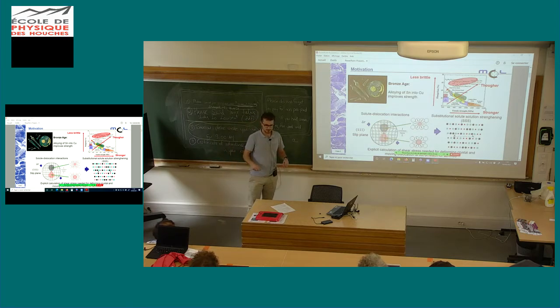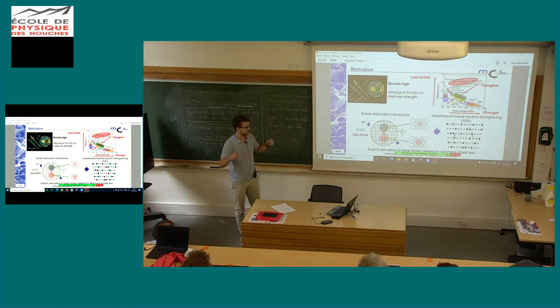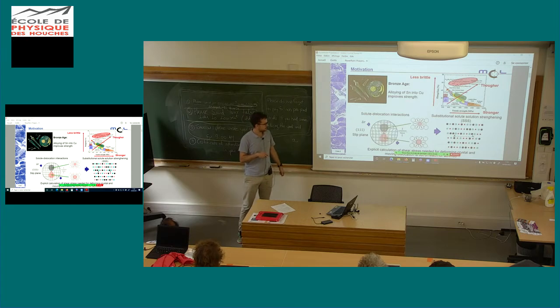So what is basically happening? If you put solutes into your alloy, it will locally distort the lattice, it will contract in some places, it will expand. And these distortions of the lattice interact with our extended defects, our dislocations, which are responsible for the plastic deformation. So you create local energy configurations for the dislocation that are favorable or unfavorable, which in fact will lead to some macroscopic strengthening effect by making it harder for the dislocation to move through the crystal. Of course, it's impossible to do an explicit calculation of that with DFT or any other ab initio methods. It's just out of reach.